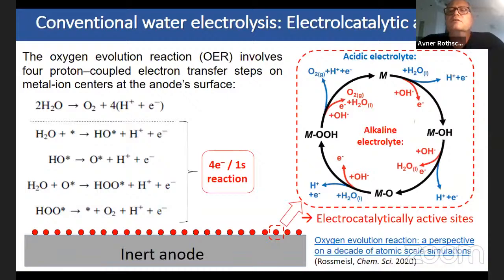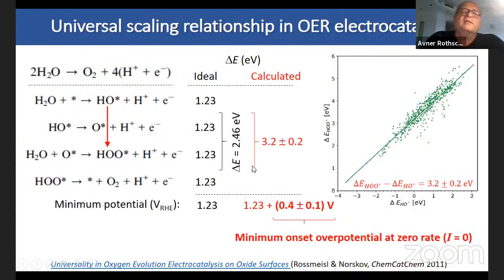So first, let's look at the conventional OER. The conventional oxygen evolution reaction involves 4 proton-coupled electron transfer steps. So it's a 4 electron per 1 site reaction, okay? And in order to have no overpotential, you must have that each and every one of these 4 steps has exactly the same energy barrier as all the other steps. But this is not what happens.